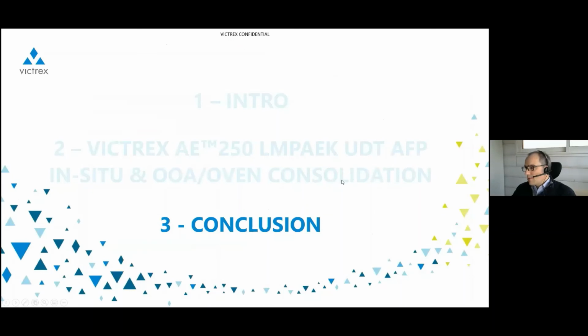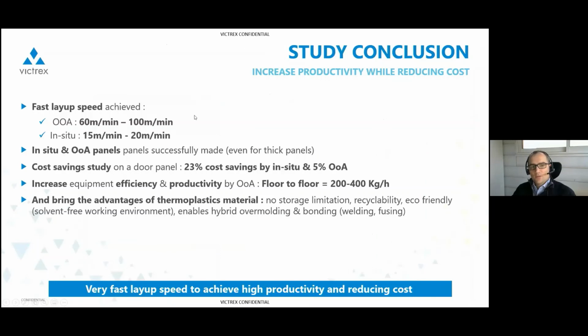So now I'm moving on to the conclusion of the presentation. What we wanted to highlight in this study is really that we can achieve fast layup speed. Obviously the highest one is with out-of-autoclave. So we say we are within the range of 60 meters per minute up to 100 meters per minute for out-of-autoclave consolidation, and for in-situ, we can target a range between 15 and 20 meters per minute. As you have seen, both for in-situ and out-of-autoclave, flat panels were successfully made, even thick panels.